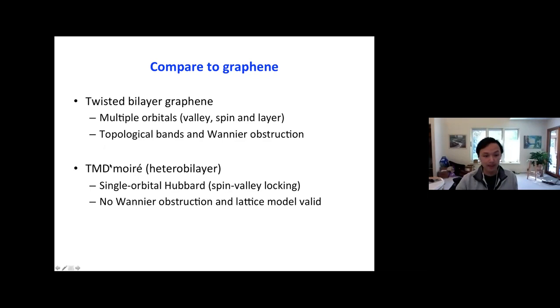And on the other hand, the TMD moiré system, especially for the hetero bilayer, in which you only have an isolated single band in the system, there's actually only one twofold degree of freedom remaining. We call it the spin valley lock degree of freedom, or you can think of it as the valley pseudospin degree of freedom. And there's no Wannier obstruction. The bands are non-topological, and the description of the physics by a lattice model is actually valid.